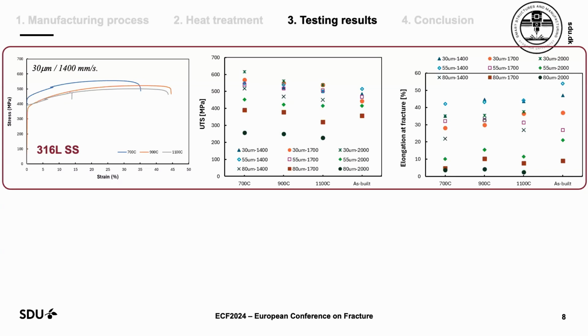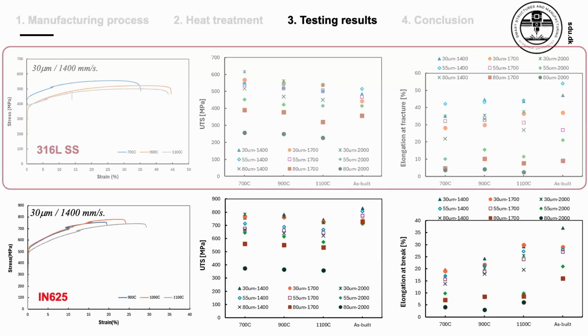We can see here, for example, going from 700 to 1100, a decrease in UTS, ultimate tensile strength. But with the heat treatment itself, we had a better UTS in some cases, while other cases were almost the same, with no big differences. But when it comes to elongation, as I said, by going to a higher heat treatment temperature, we see better ductility behavior from the material. And we saw almost the same behavior for Inconel 625, the same effect with increasing temperature.